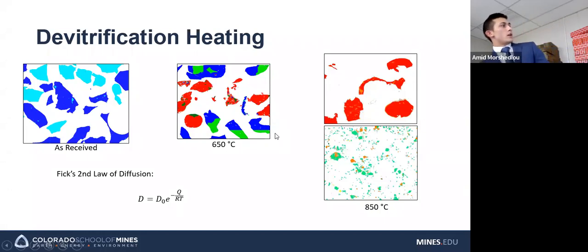So diffusivity is equal to some intrinsic diffusivity, D naught, multiplied by e to the power of negative Q, some activation energy, divided by RT, where T is temperature. What this tells us is that as a function of temperature, diffusivity goes up and asymptotically approaches some maximum based on the intrinsic diffusivity and the activation energy. So what this means is we can only jack up temperature so high and continuously get benefits. We do get diminishing returns when it comes to improving diffusivity as temperature goes up.